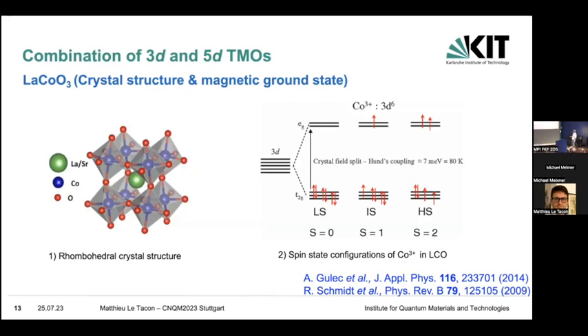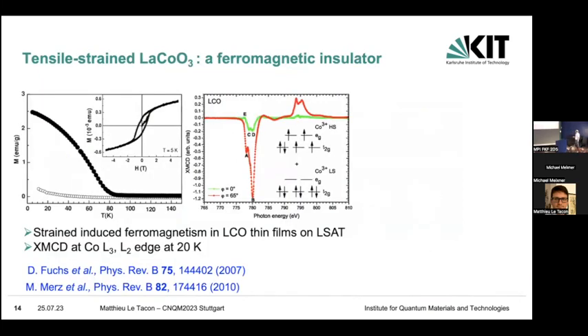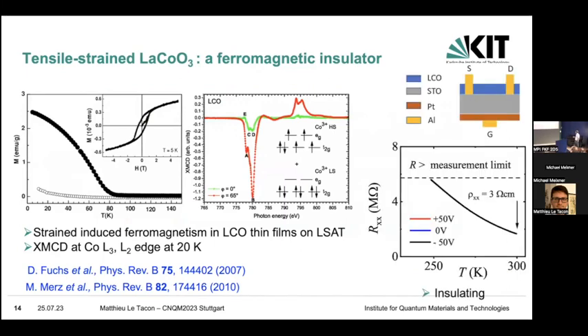So the idea here has been to grow superlattices using lanthanum cobaltate, which is in principle a semiconductor, but if you strain it, it has a complicated spin configuration, like all cobaltate compounds: low spin, intermediate spin, high spin. And it happens that when you strain this material, you actually get a ferromagnetic insulator with a Curie temperature of about 85 Kelvin. So a nice XMCD, and you can understand the ferromagnetism in this compound. And what's very important is that it remains insulating.